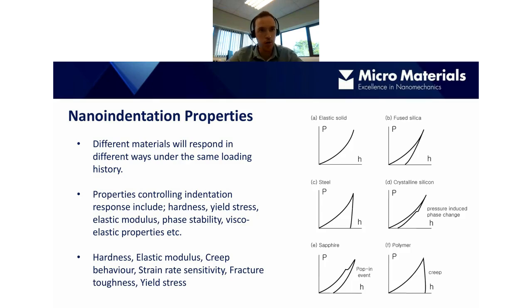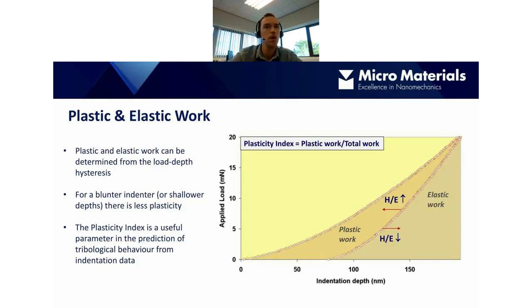Okay, so with nano indentation, from this fairly simple load versus depth curve, we can obtain a lot of information, as we've seen: hardness and modulus, but also things like creep behavior, strain rate sensitivity, fracture toughness, yield stress, and more. We can also obtain plastic and elastic work from the indentation. So the area underneath the unloading curve represents the elastic work done by the indenter, and the area enclosed by the loading and the unloading curve is the plastic work.